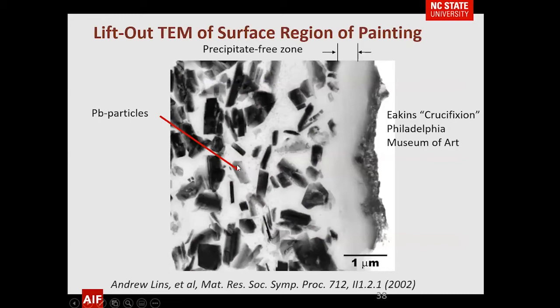This was used in many applications — here's an example of a piece of artwork that I've actually seen and held at the Philadelphia Art Museum. Using SEM EDS you can determine that these are lead particles. The question was whether the painting was being purposely darkened or whether it was from treatment and cleaning. It appears that many cleaning processes used were affecting the surface. Also interesting: it might be pretty hard to forge a painting analyzed at this scale.